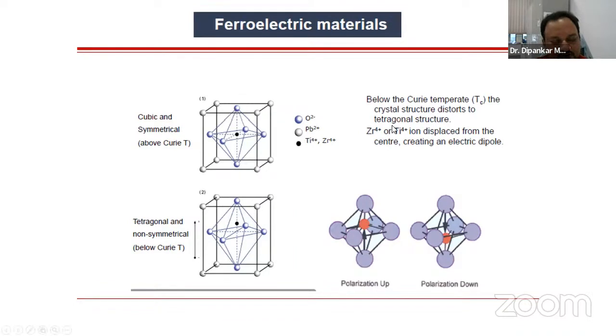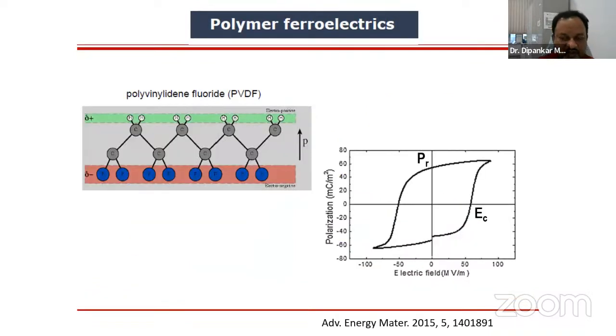That means the dipoles, which are the origin of the ferroelectricity, get randomized at this point, so you will not get ferroelectricity. So this is a cubic system, let's say, above TC. Below TC, you see the non-centrosymmetry came into the picture. This gives rise to polarization, positive and negative, which acts as a dipole. This is one of the easy pictures where you can see polarization is up, the red dot is up, so you see the arrow. But then this one is down, so polarization is down. Okay. So this is the origin of the ferroelectricity.